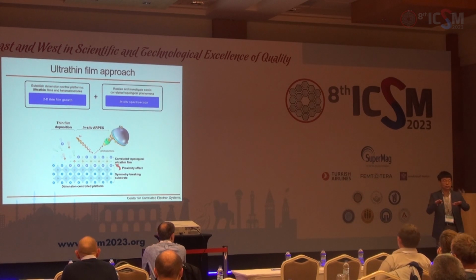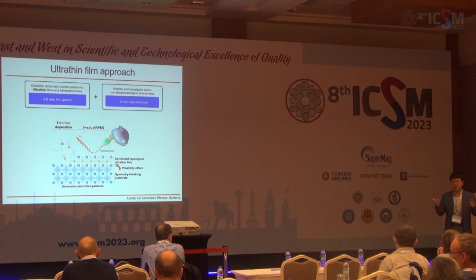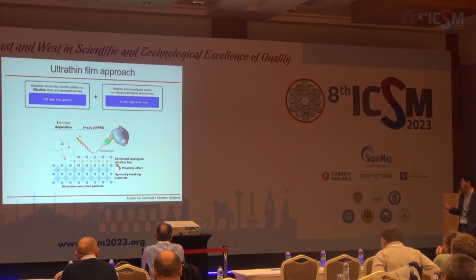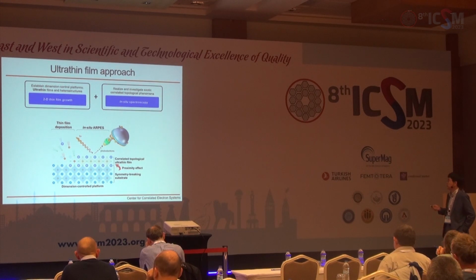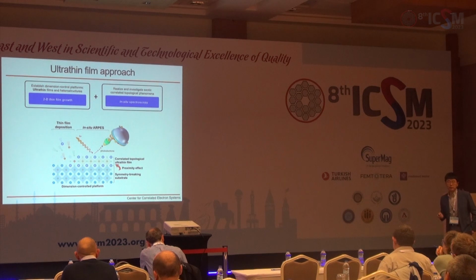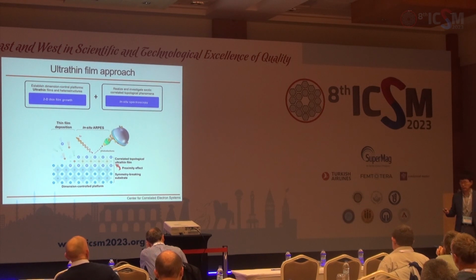step edges break the thin film into pieces. So there is a connectivity problem, and measurements are actually quite difficult. And also, if you were thinking about magnetic susceptibility, the volume is so small. That also makes measurements very difficult. Here, I do in situ ARPES, and I can measure electronic structure. And I will show you, we can also measure spin. So we can also check out the magnetism.